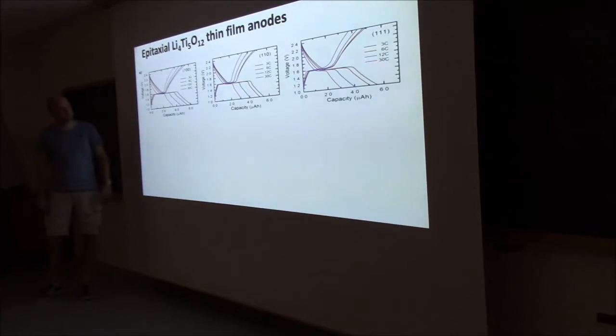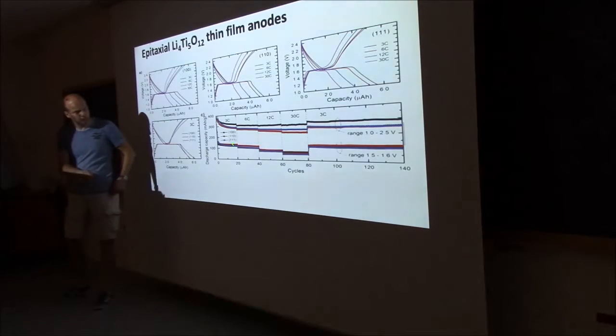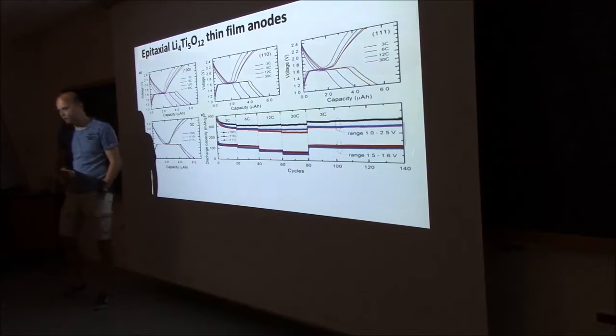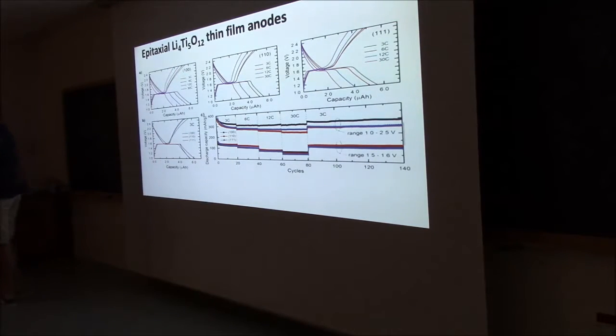If we do with different speeds, different C rates, let me put in the final picture. If I only look at this plateau region at the 1.5 volt, you can see that all three give me the same capacity. So the material works well, the same lithium going in and out.